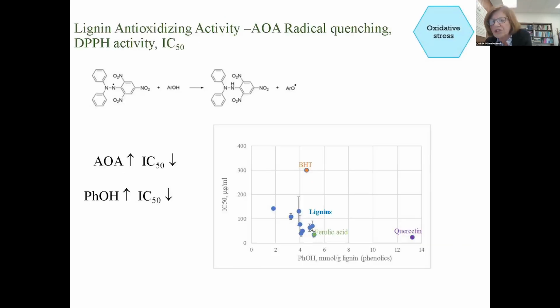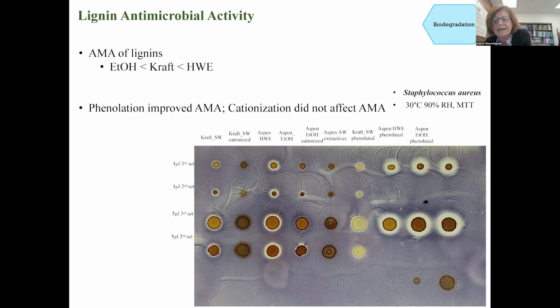Also, when it comes to chain of the radical reactions, lignin is a natural radical quencher which competes well with quercetin and ferulic acid and is way better radical quenching agent than synthetic BHT. So we could consider lignin as a good antioxidizing agent when it comes to stopping radical chain initiated reactions in degradation of polymers. And also lignin has shown some antimicrobial activities.